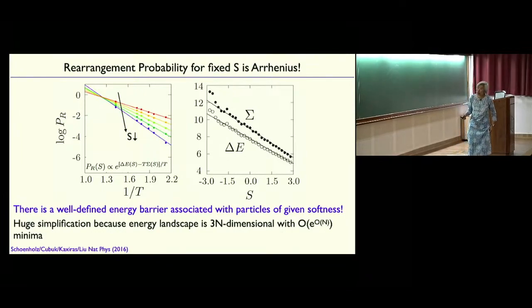The fact that there's a well-defined energy barrier is a huge benefit. Because remember, there are of order e to the order N minima in this landscape. And think of all the barriers in all the different directions in this 3N-dimensional landscape that you could go over from a single minimum. It's an impossible problem. But this is telling you the energy barrier that the particles actually go over when they rearrange, and it depends on the softness. I can have a structural quantity that I get from a snapshot that will tell me that.